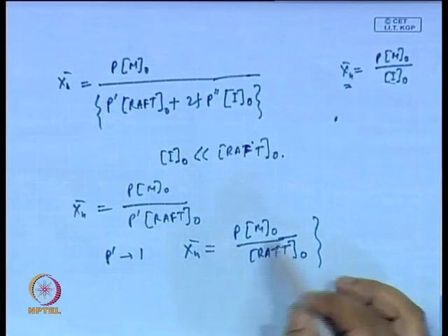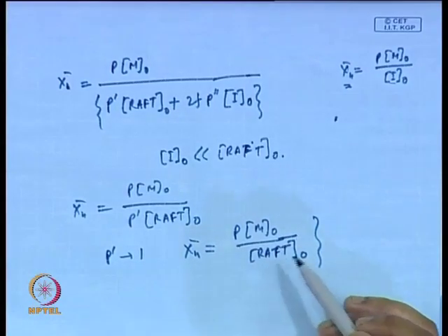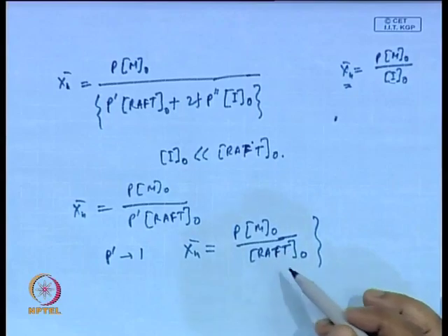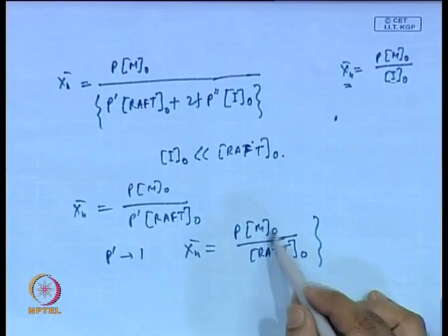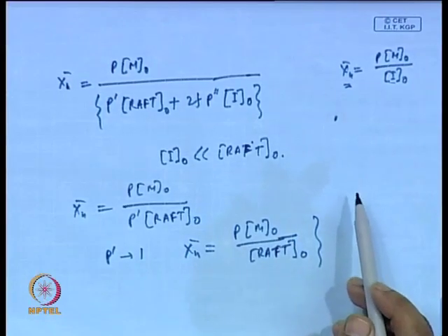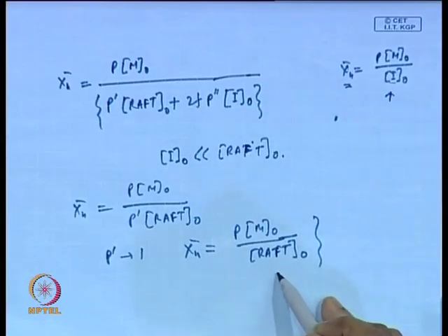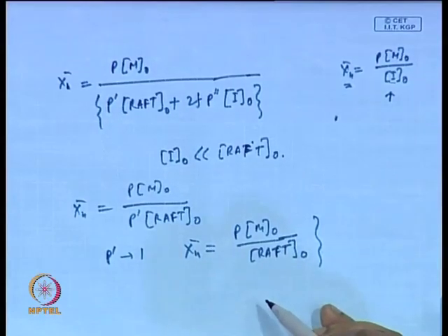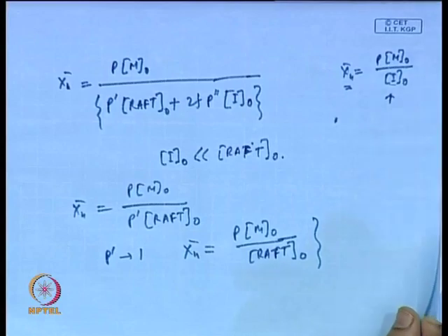So, in this case, the molecular weight depends upon the, because it is a chain transfer reagent and the chain transfer constant is much higher, so that all the RAFT reagent is taking part in the chain transfer reaction, and also because the concentration of initial RAFT reagent is much higher than the original initiator radical, we can simply write the average degree of polymerization at the end of the polymerization similarly as in case of ATRP or SFRP reaction, where I0 can be replaced by the RAFT reagent concentration at the beginning. And again, like other cases, we can utilize this reversible addition fragmentation transfer reaction for making block copolymer at the end of the polymerization if we add a second monomer.